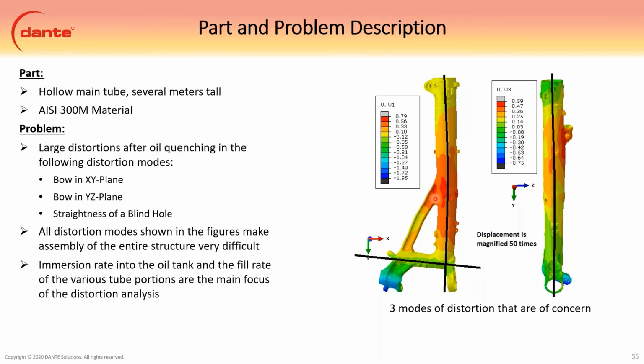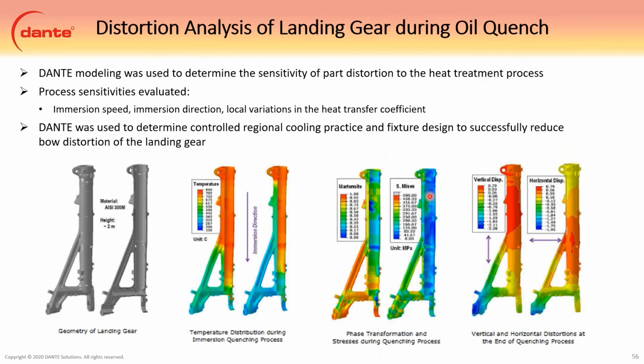As this gets dumped down into the oil, it fills up the hollow tube in the bore, and it also fills up this tube out here. All of this is very significant. So Dante can model that immersion process. For smaller parts, that immersion doesn't matter. It happens so fast that you can consider everything uniform. But with long parts like this, you have to consider the actual immersion of the part into the oil tank.